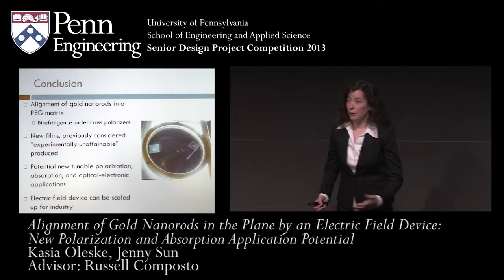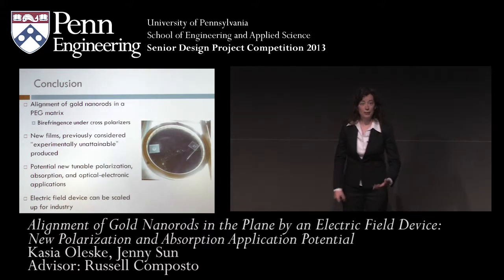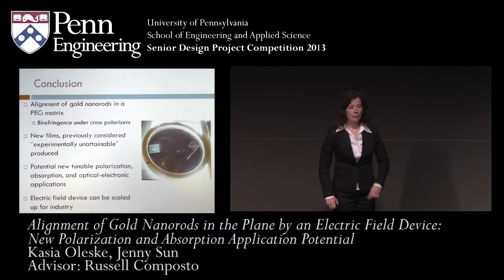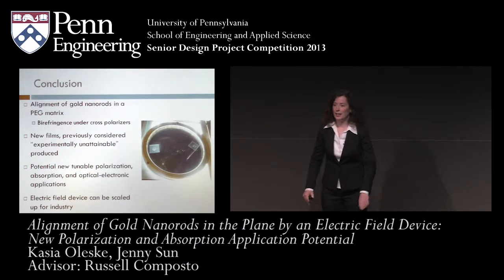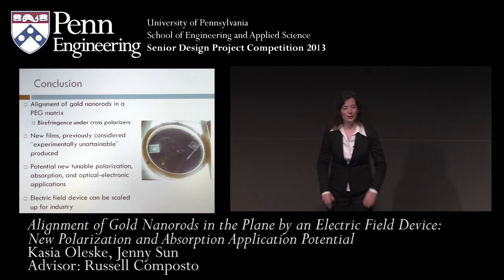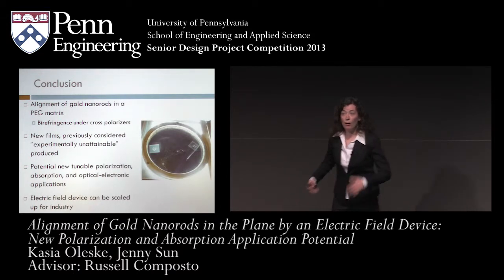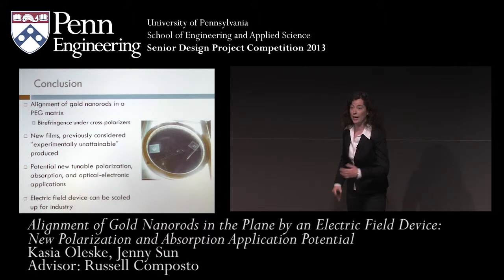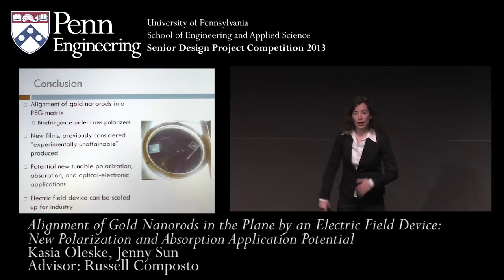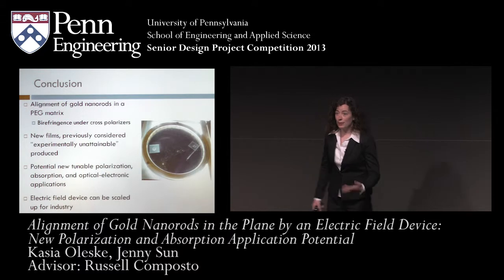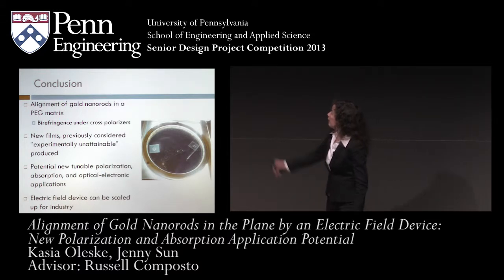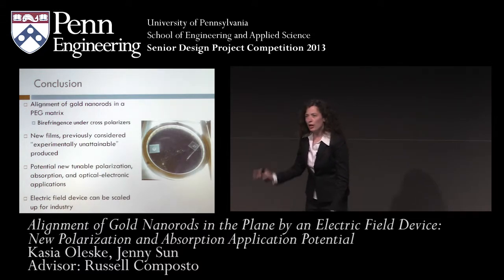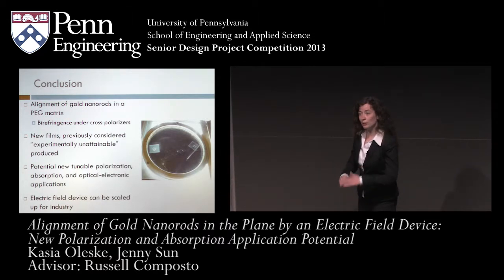So, in conclusion, we were the first people ever to be able to orient gold nanorods in the plane. In previous research, people just kind of wrote it off. They said it was experimentally unattainable and just didn't even try. And so it's really exciting because now we have all these interesting optical and polarization, absorption properties that were never before achievable. And we can even confirm this not with just 2D analysis, but with cross-polarizers.